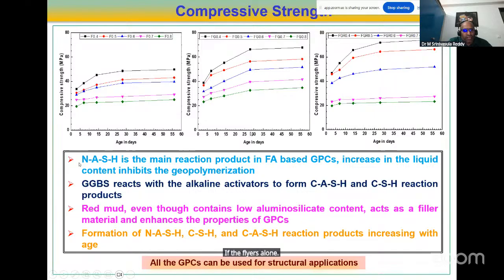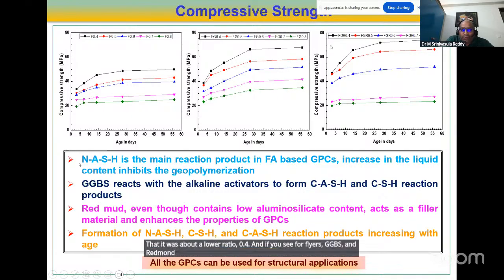If we see fly ash and GGBS combinations, it is about 66, 67. And I'm talking about only the maximum one, that is for the lower ratio 0.4. For the fly ash, GGBS and red mud combination, it is about 73, 72, 70. The main reaction product in fly ash base is NASH, sodium aluminosilicate hydrate. Increase in the liquid content inhibits geopolymerization. That is the reason. So with the increase in the ratio it inhibits geopolymerization, and fly ash based geopolymer depends mainly on the formation of NASH.